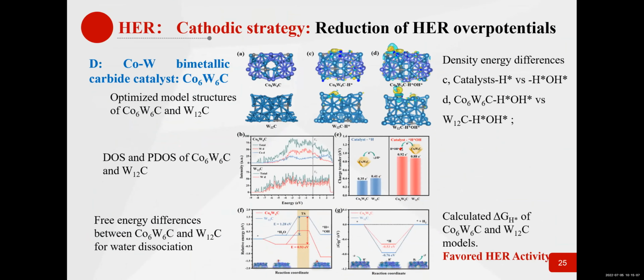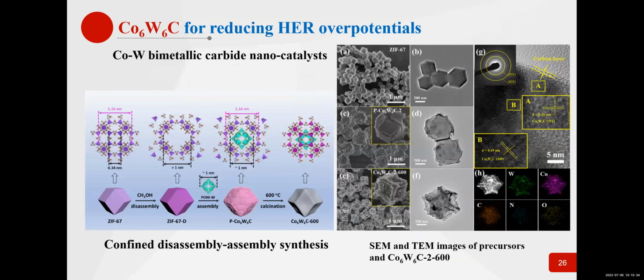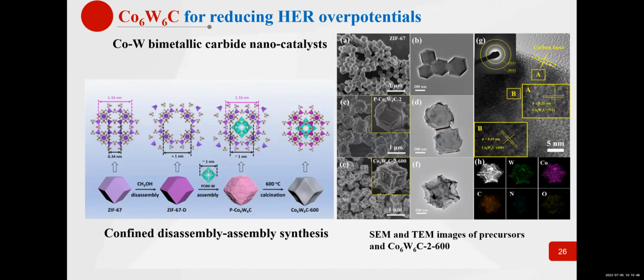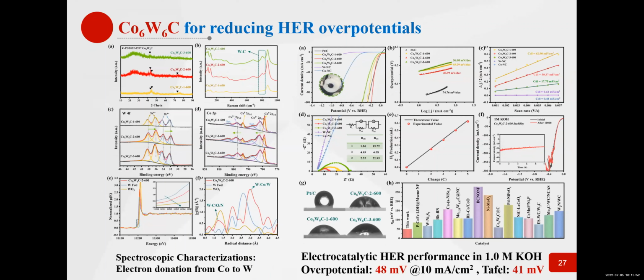And most recently, we have synthesized a very special kind of bimetallic carbide catalyst, cobalt tungsten carbide. It is a very special formulation of cobalt 6, tungsten 6, and 1 carbon. And the calculation shows that these materials have potential activities for HER. And this is the structure of the materials, and this is the morphology in the TEM images. It shows very well crystallized structures and well defined morphology. And these materials show excellent electrocatalytic HER performance in alkaline. It shows an overpotential as low as 48 millivolt at 10 milliampere per square centimeter, and the Tafel slope is as low as 41 millivolt. It shows relatively high activities for HER.